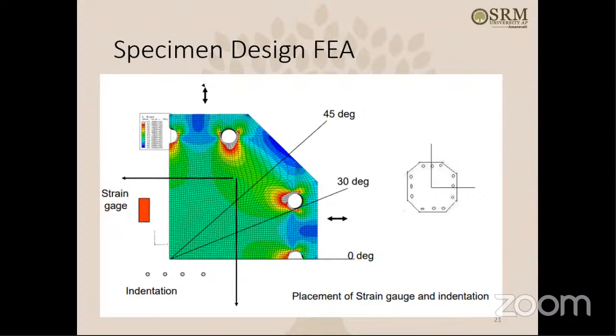Okay. So where we should place the strain gauges, that location also we found, so that it should not be near to these holes, because if you look near the hole, there's a stress concentration here. The strain gauge should be placed somewhere in the middle part here, where there is uniform strain distribution.